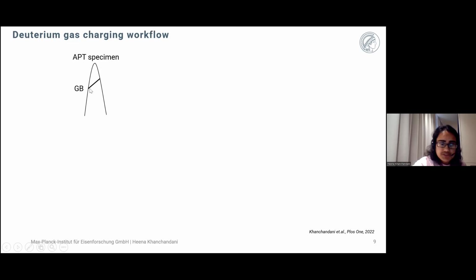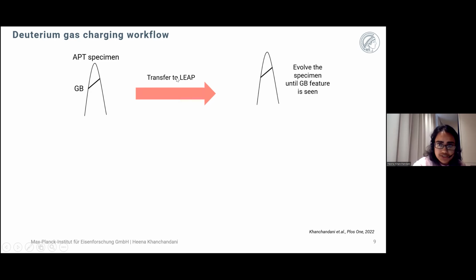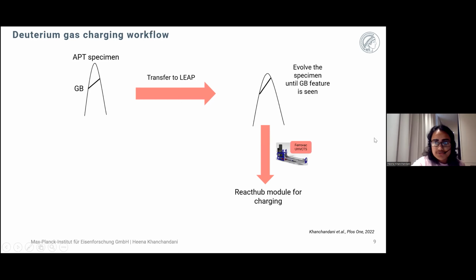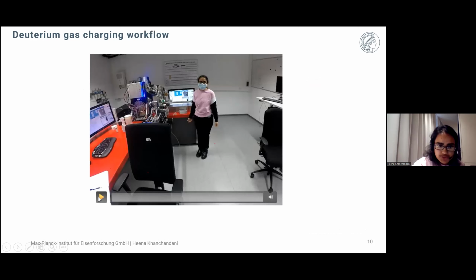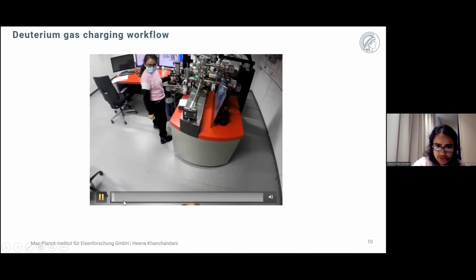An atom probe specimen containing a specific microstructural feature, in this case a grain boundary, is first transferred to the atom probe, where it is analyzed until the grain boundary feature is seen. This is to collect the data before and after charging, so that the hydrogen coming from the specimen can be distinguished from the hydrogen coming from the analysis chamber. And then it was transferred in the suitcase to the Reacthub module for charging. So I would like to briefly show this process using the videos that we recorded.